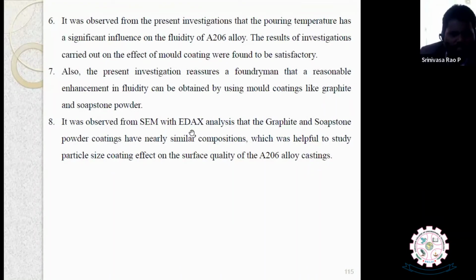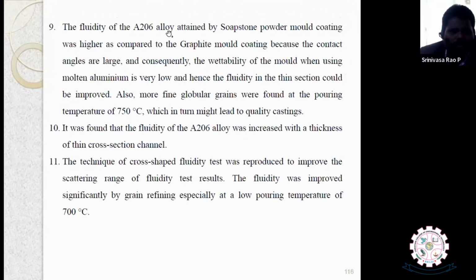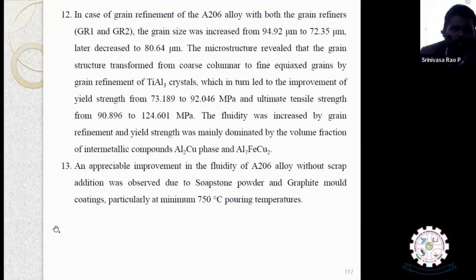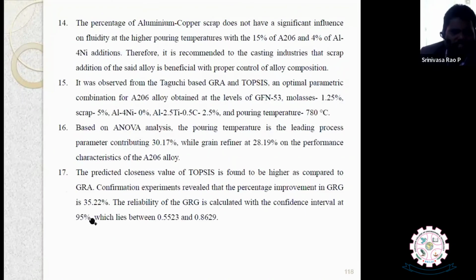SEM, XRD and EDAX analysis has been carried out, and graphite and soapstone powder coatings have nearly similar composition, which is helpful to study the particle size of the coating. The fluidity of A206 alloy attained with soapstone powder coating was higher compared to the graphite mold coating, because the contact angles are large. Fluidity increased with the thickness of the cross-section channels, and the cross-shaped fluidity test technique was reproduced to improve the scattering range of the fluidity test. The fluidity was improved significantly by grain refining, especially at lower pouring temperatures. So these are actually the results.